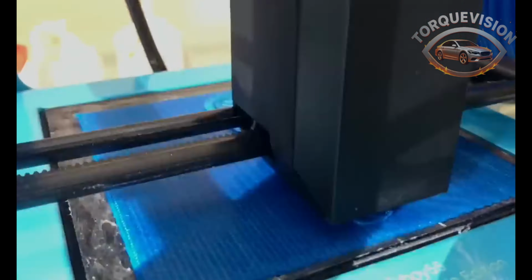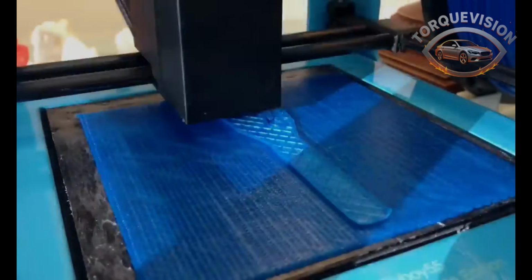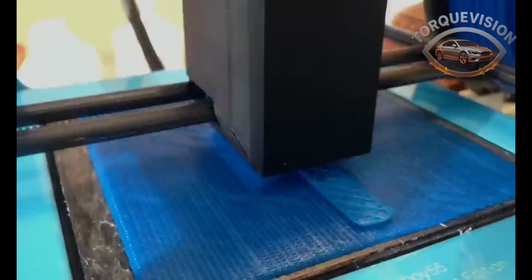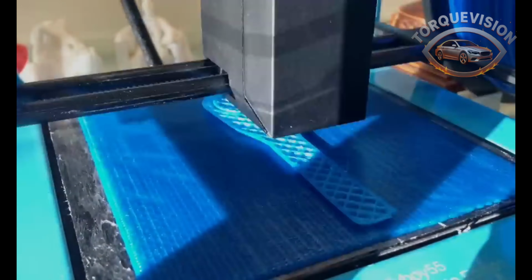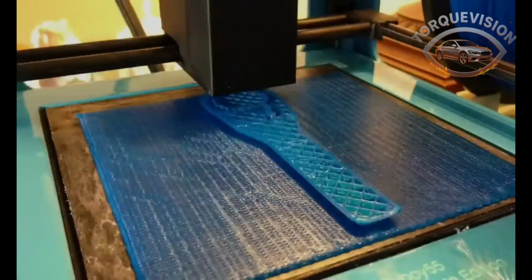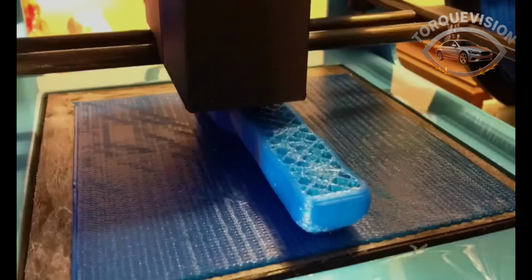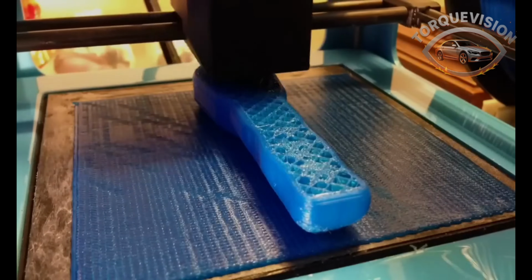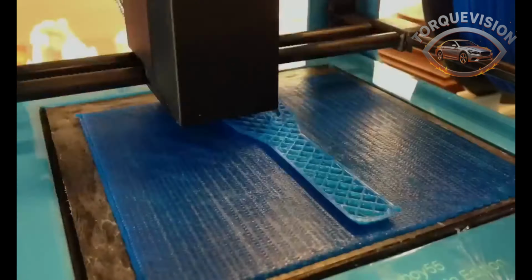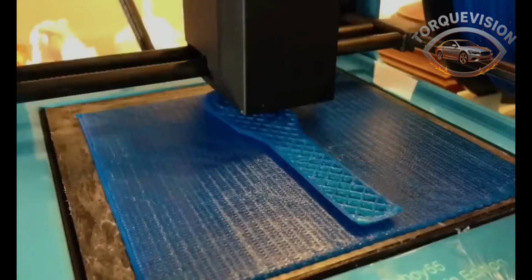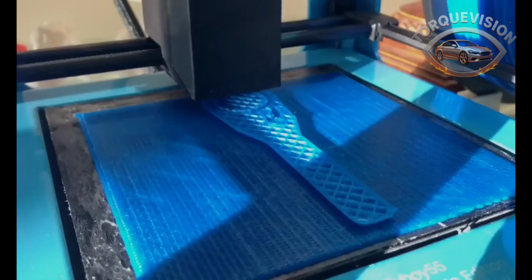It's not about infill patterns or exotic materials, it's about print orientation and perimeter count. The strongest results came from printing parts consisting almost entirely of perimeters, with minimal traditional infill. This technique, inspired by NASA's 3D printed ratcheting wrench, aligns the material grain to travel the full length of the tool, dramatically increasing strength. Post-processing techniques like annealing can further strengthen printed parts by relieving internal stresses.